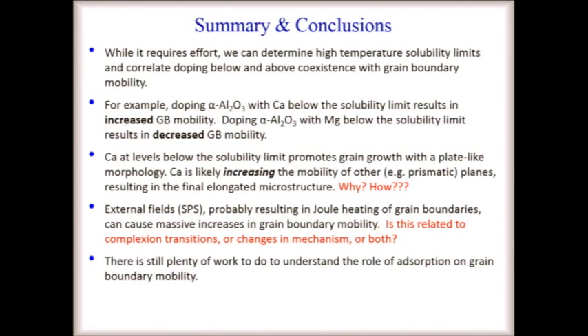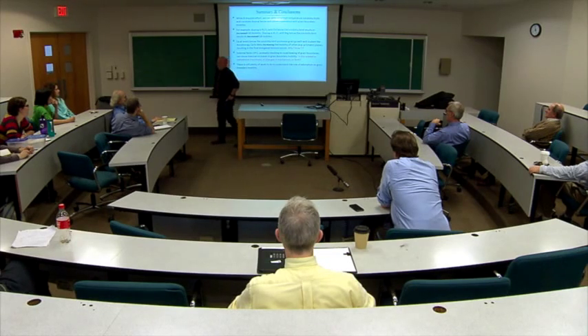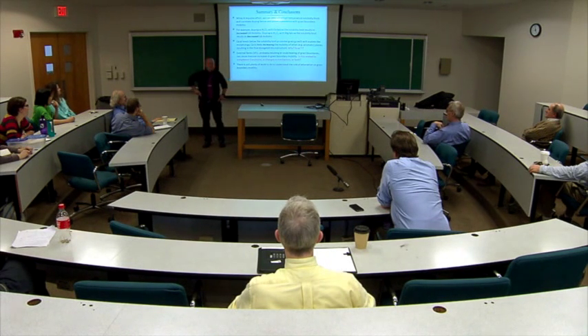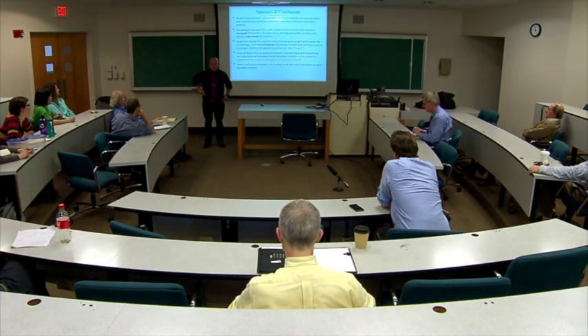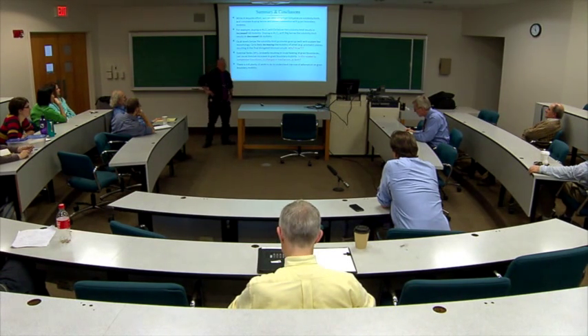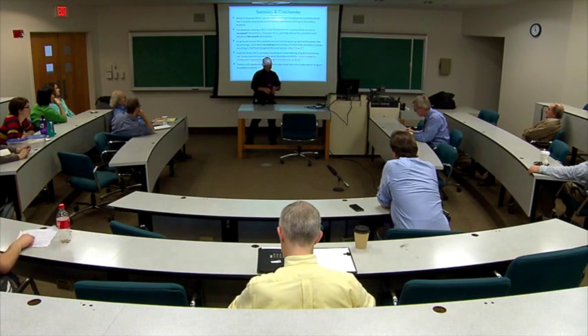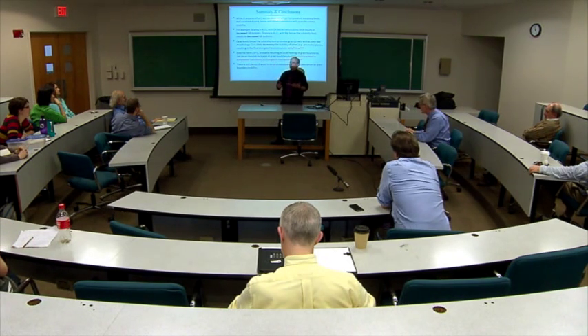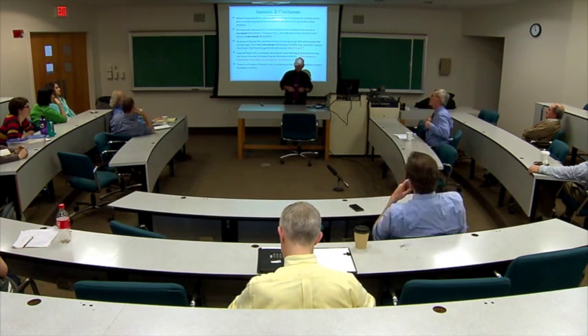I hope I convince you that calcium equilibrium segregation of calcium to grain boundaries in alumina is important. It makes the grains grow faster, although we really don't know why. And without knowing why, I don't think we can do a lot with this. The same can be said about magnesium, which slows it down. But also there, we really don't know why. And it's time to contrive some model experiments to address this specifically.